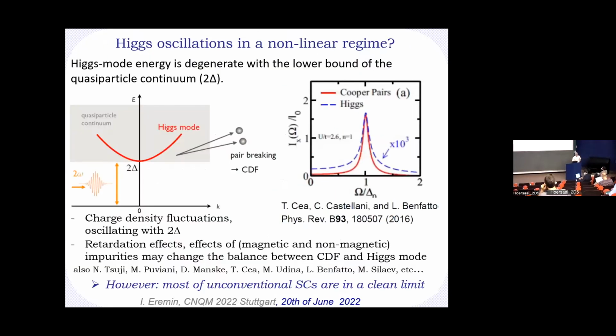Now, the problem comes if you start to do a real microscopic calculation, because the picture I've shown to you is on the level of the free energy. In a superconductor, the energy of the Higgs mode roughly coincides with the onset of the quasi-particle continuum. If you do the microscopic calculation, and that was done by Lara Benfatto and collaborators, it turns out that there is a term which does not appear if you just write a free energy in terms of the coupling of the superconducting order parameter fluctuation with the electromagnetic field, but there is a direct term proportional to the density of quasi-particles coupled to the vector potential.